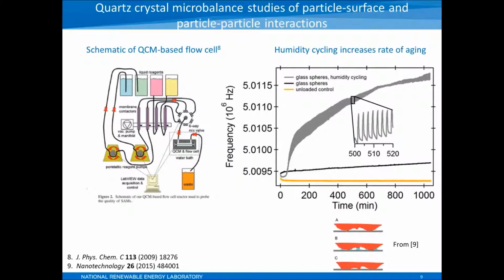So how can we probe this aging in greater detail? What I did was make use of a QCM flow cell that I built years ago to study self-assembled monolayers and liquid processes like the growth of cadmium sulfide and other aqueous chemically grown films that we use in our laboratory. I've adapted this apparatus to gas flow rather than liquids, as depicted here in the schematic on the left. We put the QCM into a little flow cell, a very small volume, 1/10 of a milliliter, and have a computer toggle gas flows. In this case, it's water saturated nitrogen and dry nitrogen over the surface of this crystal with glass spheres on it.